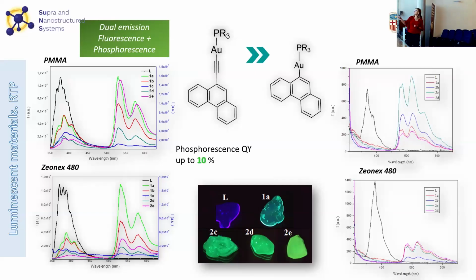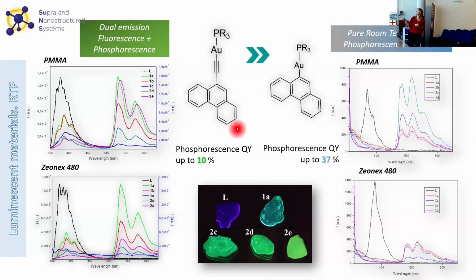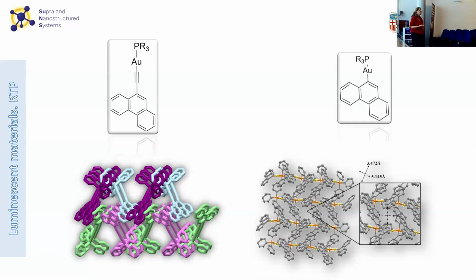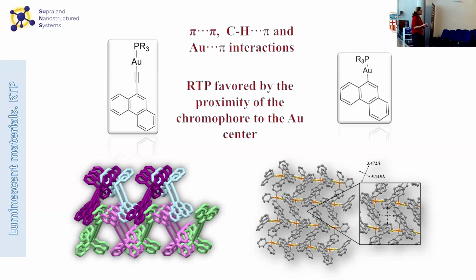While in the second case, the only part of the molecule that displays fluorescence is the chromophore alone, without the coordination to the metal center. And we have pure room temperature phosphorescence, increasing also the quantum yields of the phosphorescence emission by four times, let's say. So what is the reason for the increase of this room temperature phosphorescence? Well, we could grow single crystals in all cases also. And what we can observe is that there are some supramolecular assemblies that are induced by pi-pi stacking, CH-pi interactions, and gold-pi interactions. So the supramolecular assemblies seem the same in both families of compounds. So the only reason that can be responsible for this enhancement of the room temperature phosphorescence should be the proximity of the chromophore to the metal center. When we remove the alkynyl bond, when the chromophore is directly coordinated to the metal center, there is a clear enhancement of the room temperature phosphorescence.